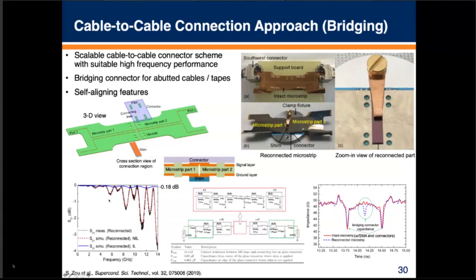a measured reconnected structure. If we had this non-ideal launch that was part of the launch structure on the cable, that would cause these resonances in the structure once it was remeasured. Then if we removed that part and looked at the intrinsic loss associated with this, we get this reconnected structure with an ideal launch. And we see that even with the connector, we were still getting about 0.18 dB for the whole structure.